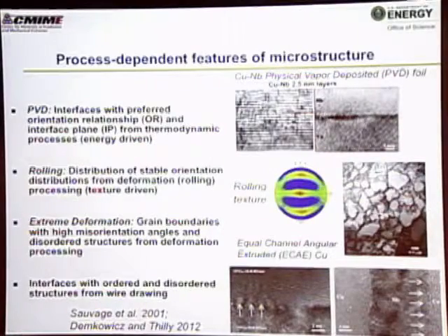And what you're going to find is that in the roll bonded material and the physical vapor deposited material, you'll get very different types of interfaces and different types of properties. So how does this work? In physical vapor deposition, we get a preferred orientation relationship and interface plane, those 5 parameters, from thermodynamically driven processes. That is, they want to land and deposit in a low energy configuration.